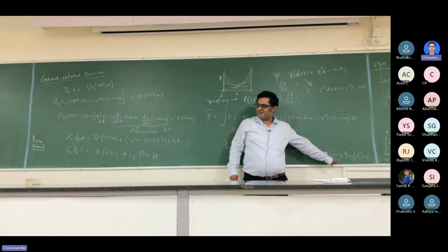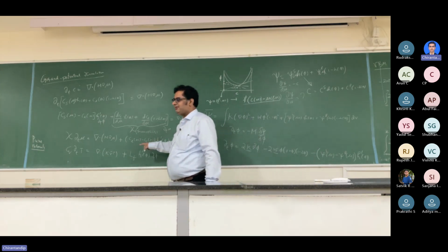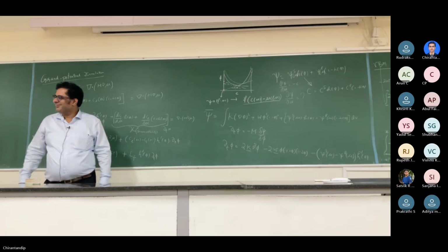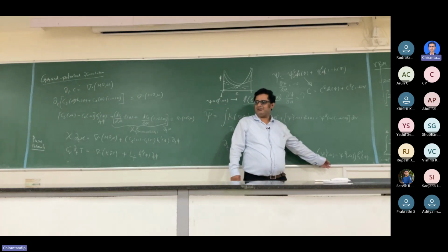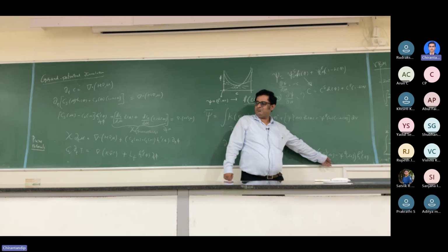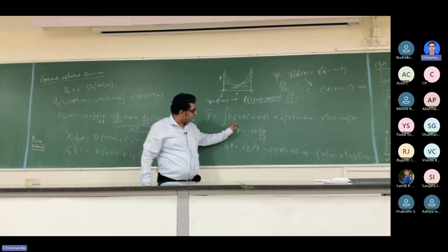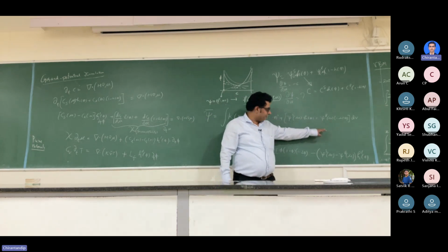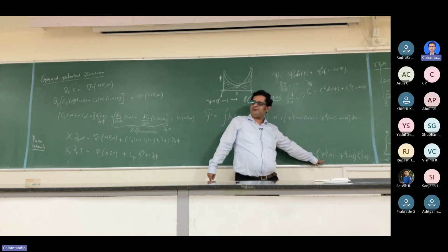The difference is such that they are at the same mu, just as it is in the pure materials, which is at the same T. What is the difference? There is no difference, except that I am just changing the variable. There is no CS and CL anymore in some sense. It is just mu sitting there. Okay. So the difference over here is only that I constructed a functional which has its independent variable as mu itself. And therefore, when I take the partial derivative with respect to phi at mu constant, this is the partial derivative.